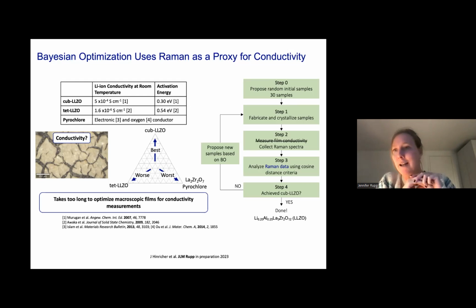But here comes a working hypothesis. If I can make dense films like I showed before, then I could argue, well, I'm at 98% theoretical density. Then I could say, well, then I just study the phase, and I could pre-decide from hundreds of samples which are the compositions that I should even make a conductivity measurement on or bring into a battery cell. And I could do that by studying the Raman spectra, and that's what we're advocating for based on the other arguments, and then have a decision matrix to say, well, how close is it to being phase pure?